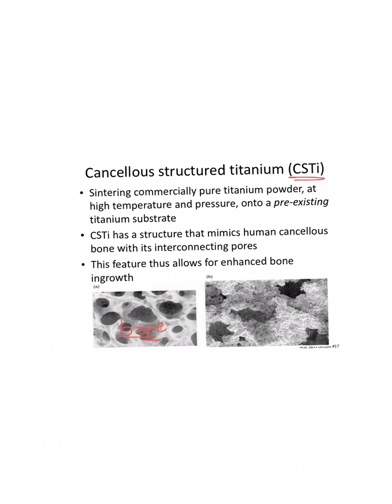And what you can do is sinter commercially pure titanium at a high temperature and pressure onto a pre-existing titanium substrate. And what they do, and you can kind of see it here, is you take that titanium, you put PMMA beads in it, which we just talked about a minute ago, and you press that onto the surface, and then you burn away the PMMA. You leave holes behind where the PMMA used to be, and the titanium all around it. And then you do this sintering process, and so the titanium bonds to itself and allows for enhanced bone ingrowth.